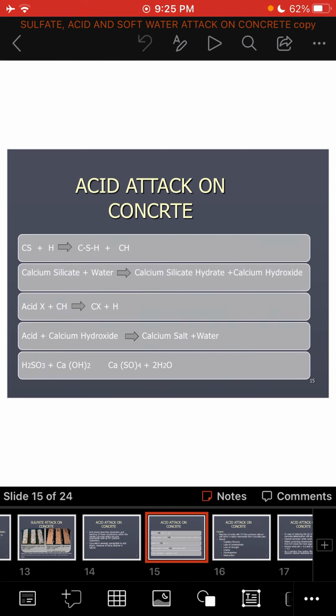Here are some formulas showing how acid attack takes place. Calcium silicate reacts with water during the initial hydration process of concrete. It will create C-S-H and calcium hydroxide. This calcium hydroxide will later on react with the acid that attacks the concrete. It will also form calcium salt and water. This calcium salt would be easily removed from concrete, and the concrete strength would be decreased.